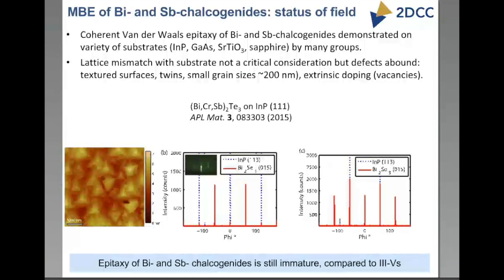Now, we've been investigating MBE growth of bismuth and antimony chalcogenides on indium phosphide, gallium arsenide, STO, sapphire, and so on, as have many other groups. And to give you an example of the kinds of defects that abound in these systems, there are textured surfaces, there are twins, there are small grain sizes, there's extrinsic doping. And if you look, for example, at this AFM scan again, you'll notice that some of these triangles have a different orientation from other triangles, right? And if you do X-ray diffraction scans, what you find is clear presence of twinning.